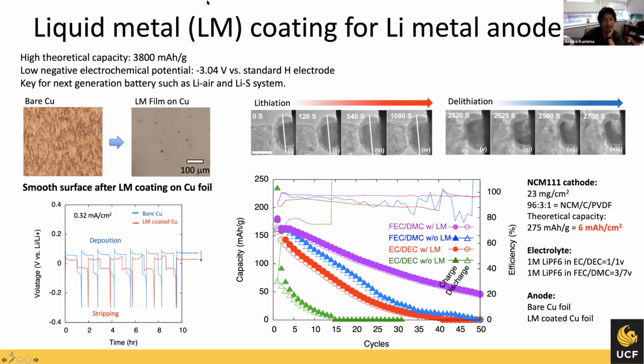What you do here is coat the liquid metal on this copper current collector. What you see is bare copper, which is rough on the surface, but by applying the liquid metal on the surface, you can create a very smooth surface that promotes uniform deposition of lithium. And this liquid metal is based on gallium, which reacts with lithium, so it attracts lots of lithium. So the wetting performance of this liquid metal is good against the lithium.